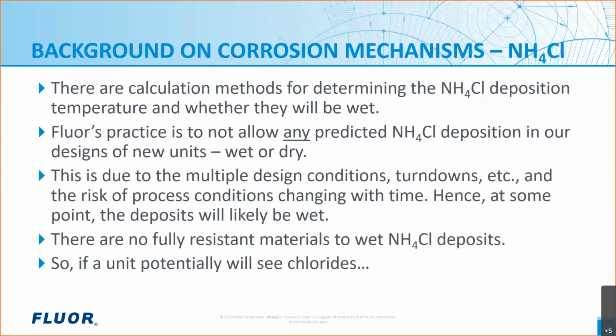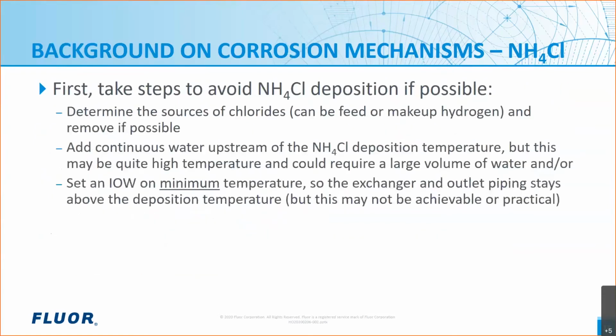So if a unit will potentially see chlorides in the effluent, our steps are, first, we will try to determine the source of these chlorides. The chlorides can either be from the feed or the makeup hydrogen, and we can study ways to possibly remove them. If the chlorides are coming in with the feed to the hydroprocessing unit, it might be that the crude unit could improve the desalting or somehow remove more chlorides from this feed source. And or if it's the makeup hydrogen, which could be coming from a CAT reformer unit, maybe we can add a better absorber in the CAT reformer unit so that the makeup hydrogen doesn't have the risk of chlorides coming to the hydroprocessing unit. So that's one of the first steps that's done.